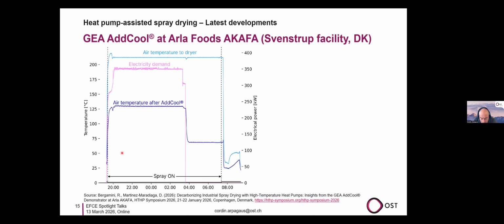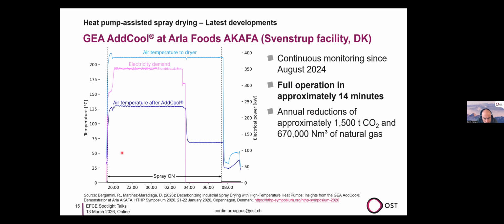What is interesting are first monitoring data. This system has been running since August 24, and you see here on the left some temperature measurements over time. Here is where the spray dryer starts, and in the first minutes, probably 14 minutes, are needed to get this heat pump fully operational. And then afterwards it keeps the temperature as required, so the air temperature at about 130 degrees and so on. Now they calculate how much CO2 they can reduce compared to natural gas. Here you see the numbers: about 1,500 tons CO2 and 670,000 norm cubic meters of natural gas.